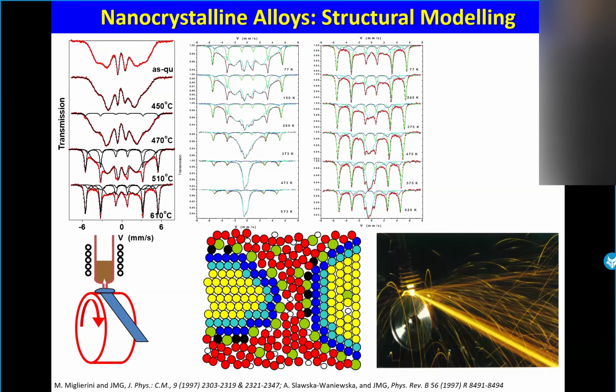It is necessary to introduce 3 components. And of course, we were able to consider that we have the amorphous matrix, remember, with disorder, and it is shown by red atoms. We have the crystalline grains by yellow ones, and we have the interface. And the interface plays an important role because you have the black atoms. They correspond to some molybdenum or zirconium, which create a kind of wall to prevent the growth of nanograins. So it was perfectly possible to describe it with only 3 components.